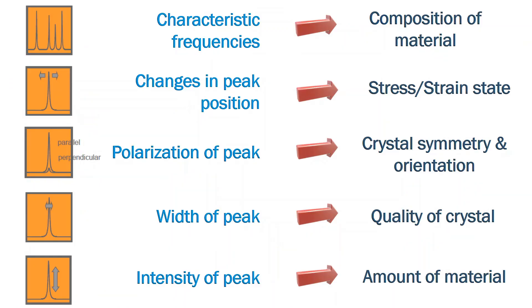There are a number of features that we monitor in the Raman spectra to identify what's going on in your sample. Firstly, we study the characteristic frequencies that are present in the spectra to interpret the composition of the material generally. There is a caveat, however: we cannot identify the elements present via this technique. So it is a good idea to couple this with some other elemental analysis if you do not know what elements are present.